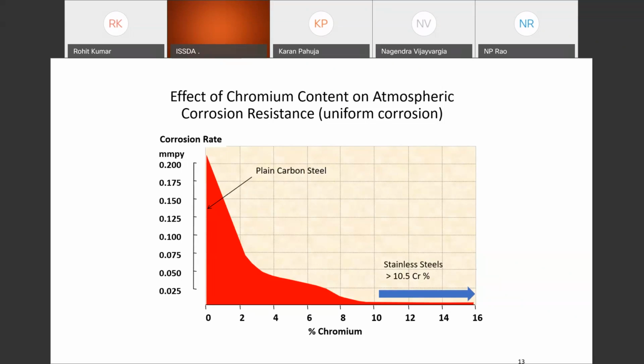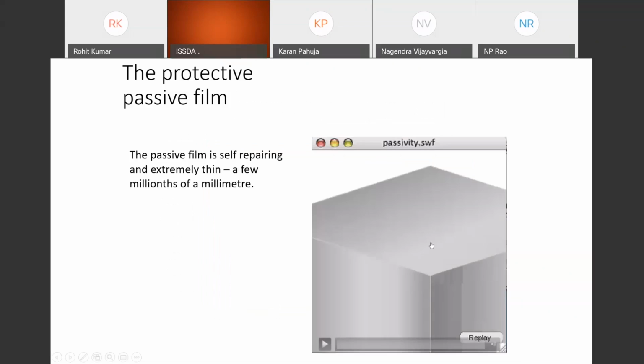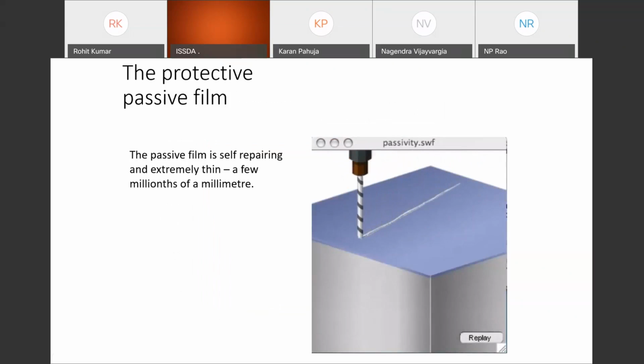Why does it become stainless steel after this addition of chromium? If you look at this picture, this video, chromium in steel combines with oxygen and forms a passive layer of chromium oxide. Now, you have to cut, weld, and bend the material. When you cut or scratch it, this layer gets disturbed. But again, there is oxygen in air, and chromium is available in the material itself. So this again forms a passive layer of chromium oxide. So this layer is self-repairing. Even if you keep disturbing it, scratching it, it will keep forming the chromium oxide layer.